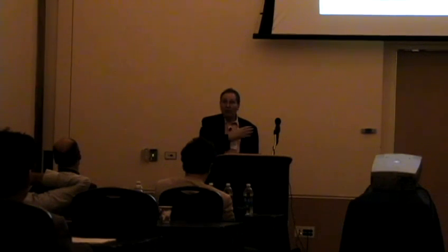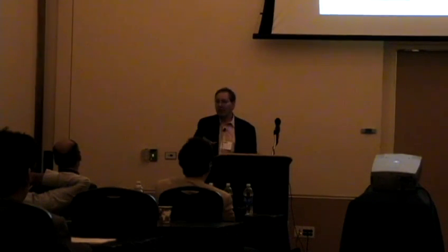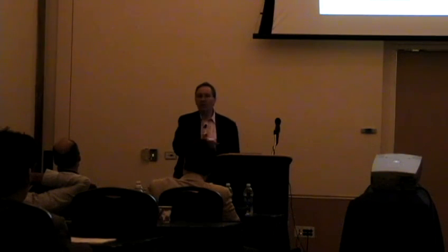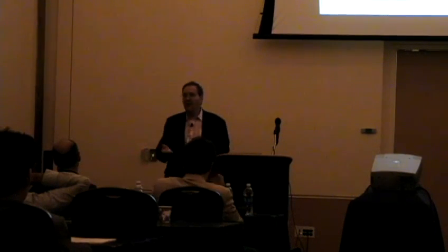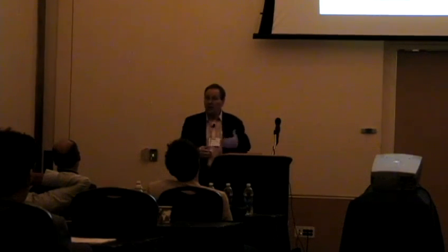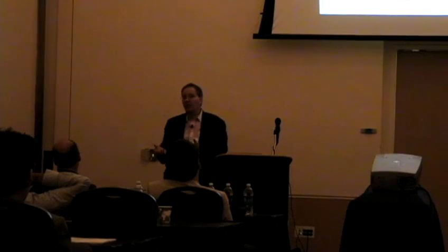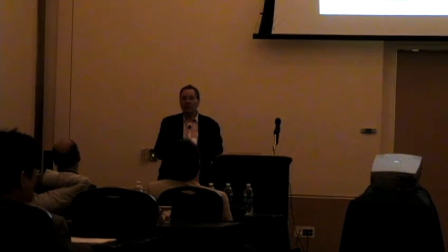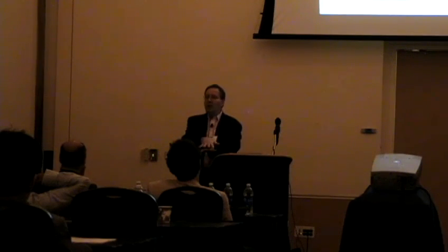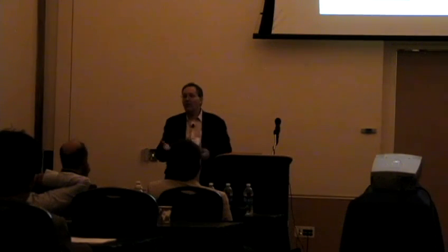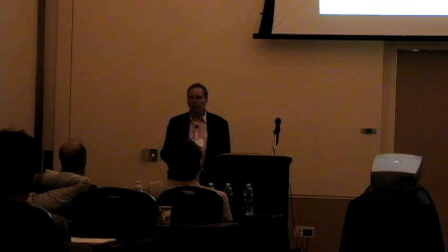As I showed you, I showed some evidence from nonlinear transport, which is disputed because it's just a resistance curve. And there are lots of ways of getting nonlinearity, although I think it's likely to be associated with nonlinear transport. So that means that the field is moving these things around. Again, it's just very difficult to control. You have to have a thin film, you have to have an oriented thin film, it has to be epitaxial, you know, all of those good things that theorists take for granted